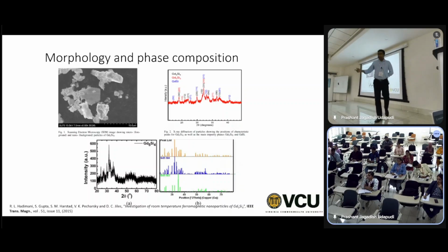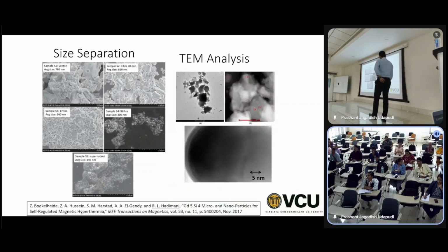So if you remember, in my first class or second class, I was showing the peaks of simple cubic, SiO2, and other materials. They were only 3 peaks or 4 peaks, clean XRD signal, right? That's not possible with crystal structures that are hexagon or orthorhombic or monoclinic.